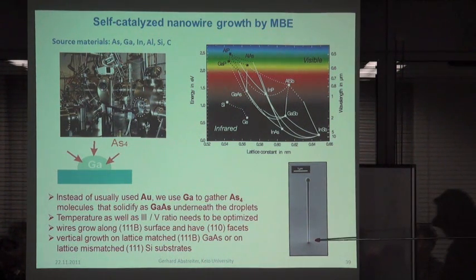Now this is an example of such a gallium arsenide nanowire where we used a little too much gallium, so the gallium droplet is growing. And that's why it's inverse tapered. If you have a little too less, then it's tapered in the opposite direction. And if you adjust it correctly, then you get very straight gallium arsenide nanowires.